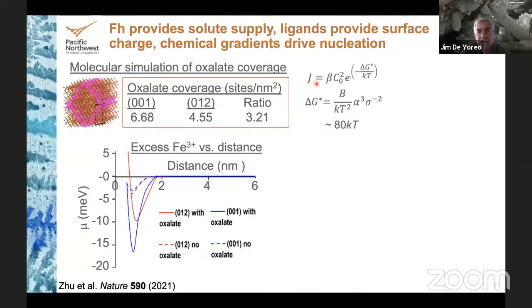So if we look at the nucleation rate, it's exponential in the free energy barrier, and it goes as the concentration to the second power. The free energy barrier itself scales with two important terms. One is a cube of interfacial free energy, and the second is the quadratic term in the square of the supersaturation. This term can't change nucleation rates very much because it's only a quadratic, but you only have to change these terms by a little bit to get a huge change in nucleation rates.